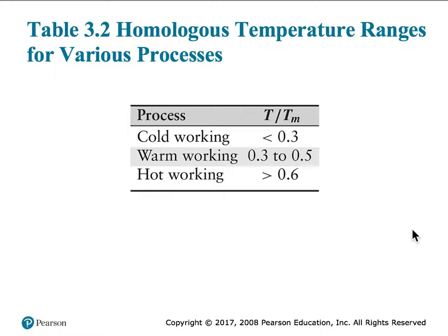As I said to you, the typical differentiation between hot working and cold working is approximately half the melting point in degrees absolute. This textbook claims that cold working is only if it is less than 0.3, warm working is between 0.3 to 0.5, and hot working if it is above 0.6 of the melting point in degrees absolute. But typical numbers are half the melting point in degrees absolute. This is the same temperature which takes into account the creep processes that can happen in a more accelerated fashion if you go above that temperature. So T is the operating temperature and Tm is the melting point.